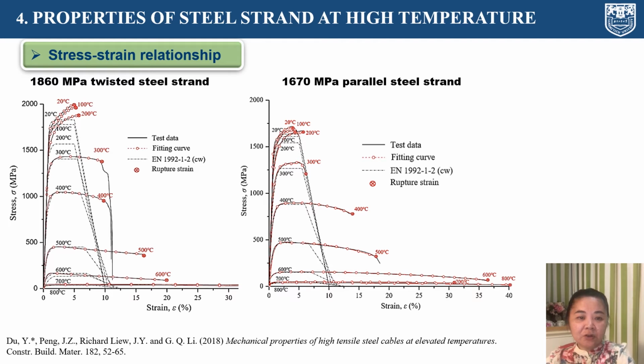The full range stress-strain relationship at elevated temperature was captured by a DIC system for the first time, as shown in the figures. Fitting curves are different because of the clamping action on the twisted wires. The effective yield strength at 1.25% strain rather than 2.0% for twisted strand is proposed.